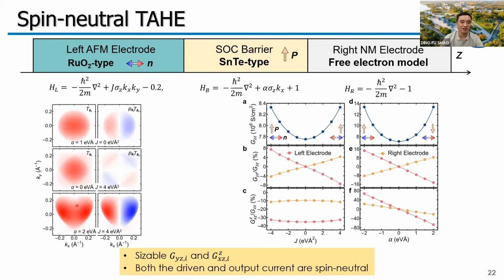And also in this transmission pattern, we can see we have a very strong unbalanced distribution along the y direction, which generates a large tunneling anomalous Hall effect with a Hall angle about 4% in the right electrode. This value can be comparable to the Hall angle in the conventional ferromagnetic bulk metals. And if we consider the spin polarization of the transmission, we find the spins are anti-symmetric along the x direction, which will generate a sizable tunneling spin Hall effect along the x direction. We find that these two effects can also emerge in the left electrode, and the Hall angles can be even larger.